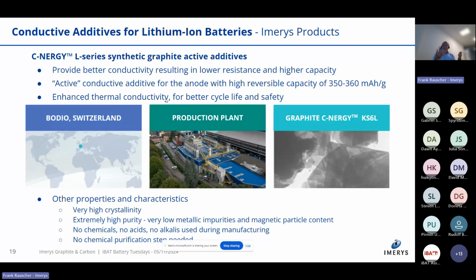And the faster you charge, of course, the more thermal energy is being released, and to get that out of the battery, we have data showing that our high aspect ratio synthetic graphite helps you with keeping your cells at a comfortable temperature. The higher the temperature, the more side reactions you have, which will impact cycle life negatively and, ultimately, also safety. So the material coming out of Bodio, very high crystallinity.